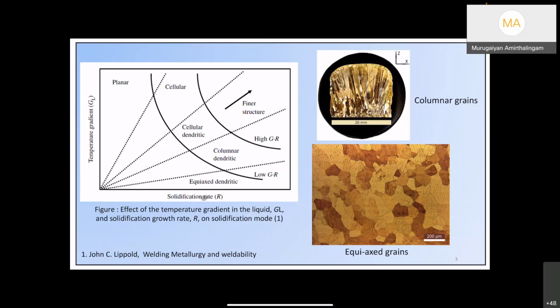Ideally, when a liquid solidifies in a melt pool, even when water freezes, the microstructure it forms is controlled by two important parameters: the temperature gradient at the solid-liquid interface and the rate at which the solidification is progressing. If you freeze water, sometimes you see very clear ice cubes, sometimes you see opaque ice cubes. So why is the difference?